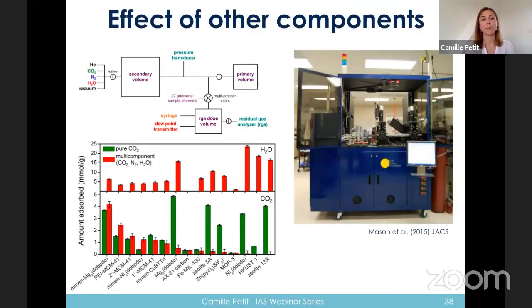Going beyond that, you want to mimic real conditions. And so ideally, you want to expose your material, when you test it, to a real mixture of gases. Here, that was done using this setup at Berkeley, where they had a mixture of components of CO2, nitrogen, and water, and they could see how the performance changed, whether they were considering pure CO2, which are the green bars here, and the multi-component stream. Again, for some materials, this didn't make much of a difference, but for others, you can see a dramatic decrease. That is, for instance, the case of MOF 74, which is this one, or zeolite X, which is famous for absorbing a lot of water.